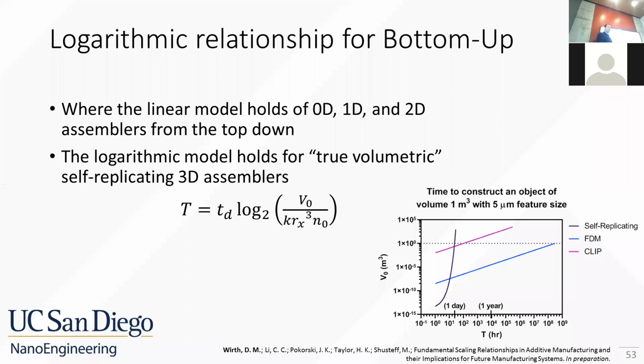Using a highly parallelized process such as CLIP with a 200,000 by 200,000 pixel array with 5 micron pixels, it would take roughly 100 hours to produce such a structure. Using a bottom-up self-replicating paradigm of manufacturing, it would take under a day to produce the structure.